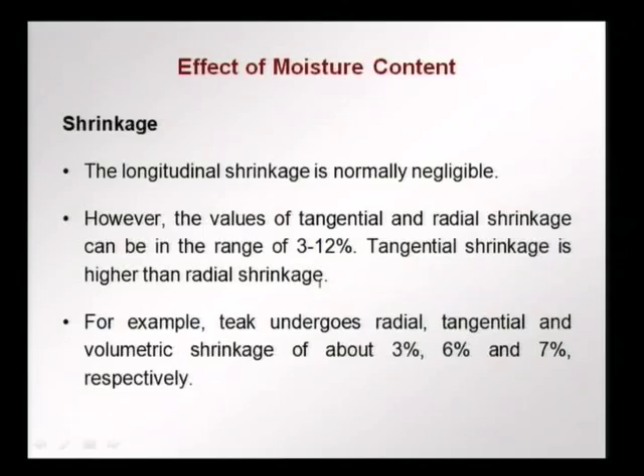So if we look at values, as I said, the longitudinal shrinkage is very small, it is normally negligible. However, the values of the tangential and radial shrinkage, these are strains, can be in the range of 3 to 12%, the tangential shrinkage being higher than the radial shrinkage. Some values for teak: radial shrinkage can be about 3%, tangential shrinkage can be 6%, and overall volumetric shrinkage can be about 7%. The shrinkage in the longitudinal direction is almost nothing for teak wood.